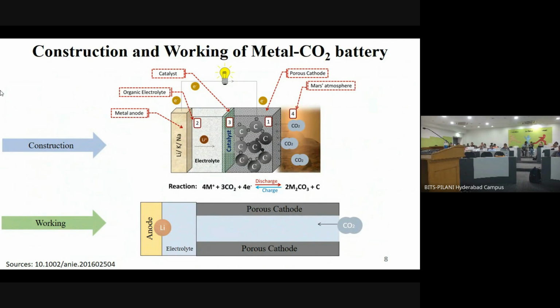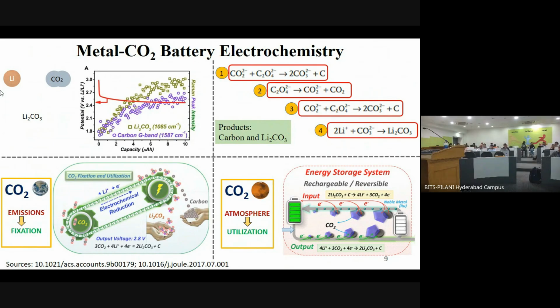This is your metal anode. Then there is the electrolyte. Then there is a catalyst. I will come to that: what is the role of the catalyst here? And this is your porous cathode through which you pass the CO2, and that's where the reaction happens. This is the primary reaction, as per the currently established mechanism. Lithium reacts with the CO2 and forms the metal carbonate and carbon, which are solid products. That is where you need the porous cathode, to accommodate those solid products on active sites, other than providing pathways for the CO2 in this battery system.